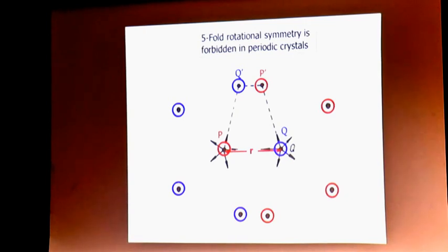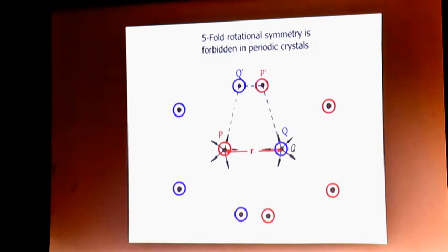If you try the same experiment for four-fold rotation symmetry, you'll see it is allowed. Three-fold, it works. Two-fold, works. Six-fold, it works. Five? No. No five-fold rotation symmetry. As I said, I passed the exam.